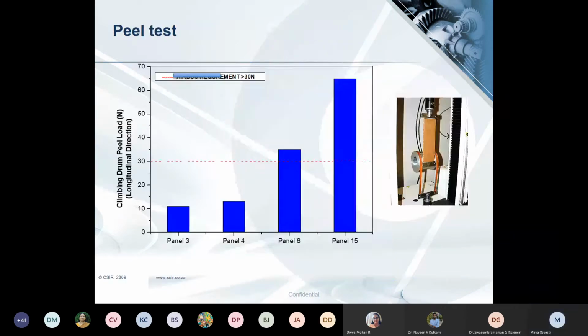So this is the peel test, and the peel test basically measures the adhesion between the skins and the core. And the requirement was that it should be greater than 30 newtons, and you can see panel 15 is well above the requirement.